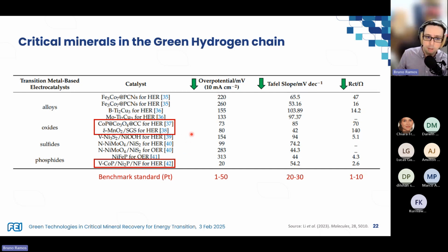So we see the strongest contenders here are actually these guys that I marked in red. So oxides, we have cobalt, phosphorus, and again cobalt on carbon, and here we have manganese oxide. And the phosphides, which are a combination of vanadium, cobalt, and phosphorus again, and nickel. And this is the benchmark standard, which is platinum. Platinum is the benchmark material used for electrolysis.